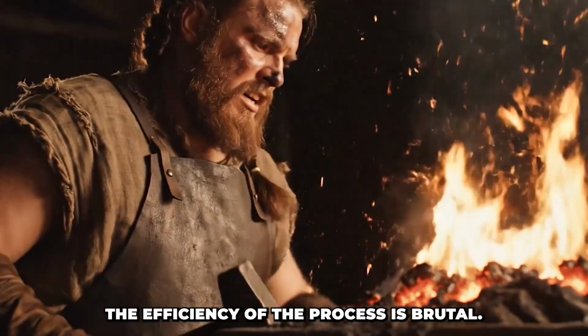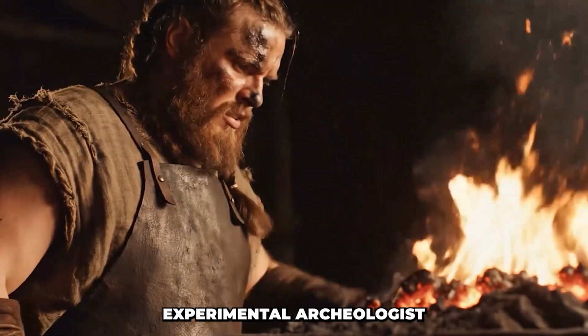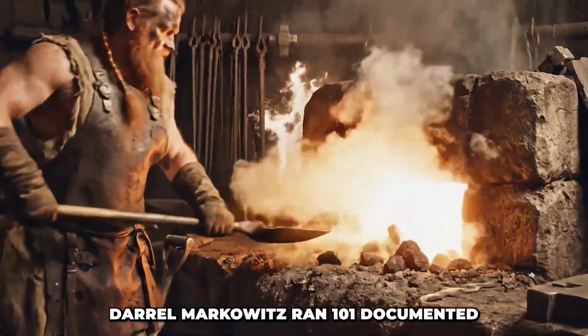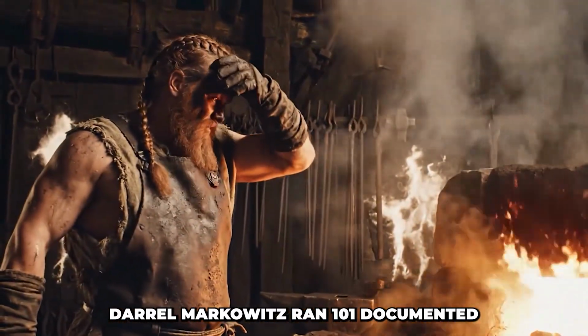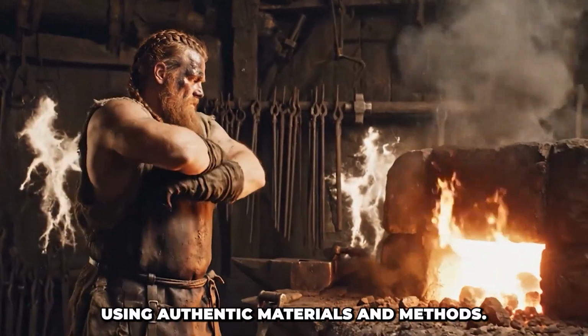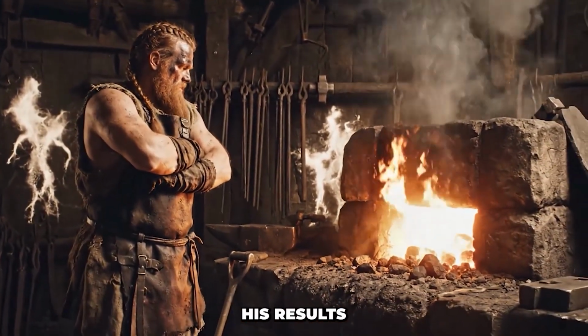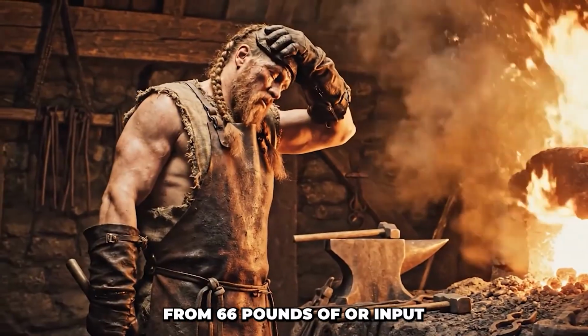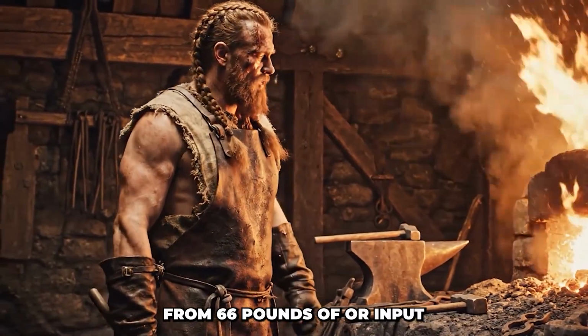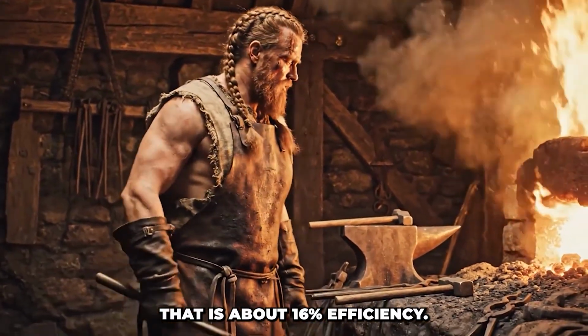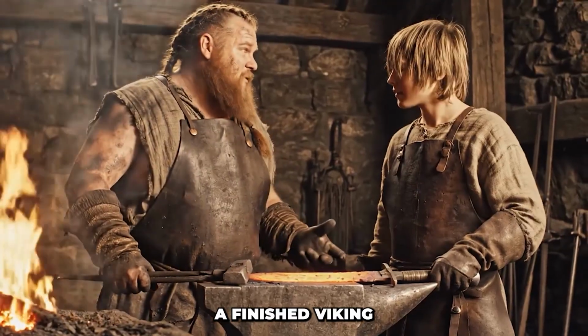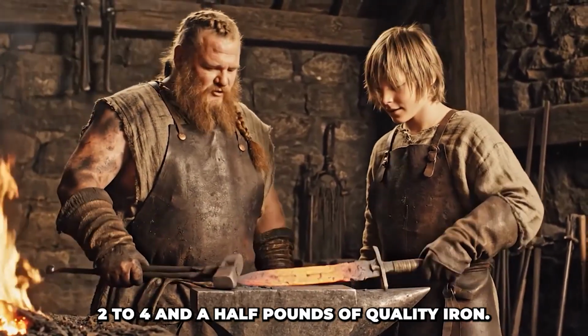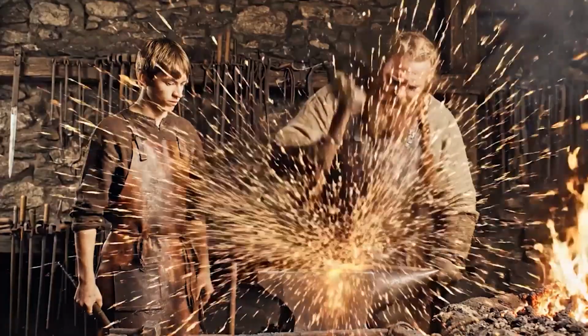The efficiency of the process is brutal. Experimental archaeologist Daryl Markwitz ran 101 documented smelt tests using authentic materials and methods. His results, roughly 11 pounds of bloom from 66 pounds of ore input. That is about 16% efficiency. A finished Viking sword requires 2 to 4.5 pounds of quality iron. Do the math.